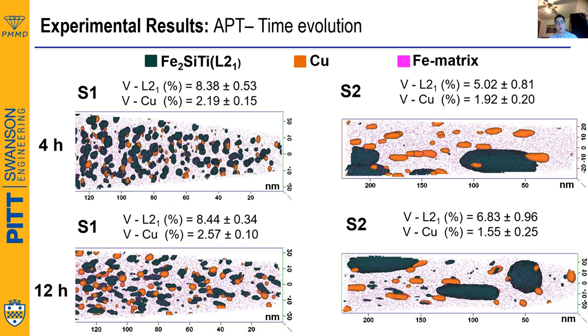The volume fraction of copper in these samples is similar to the one reported in previous HSLA studies strengthened by copper and M2C carbides, between 1 and 3%. However, having a range between 5 to 8% volume fraction of L21 confirms the advantage of this intermetallic phase as a suitable strengthening precipitate phase.